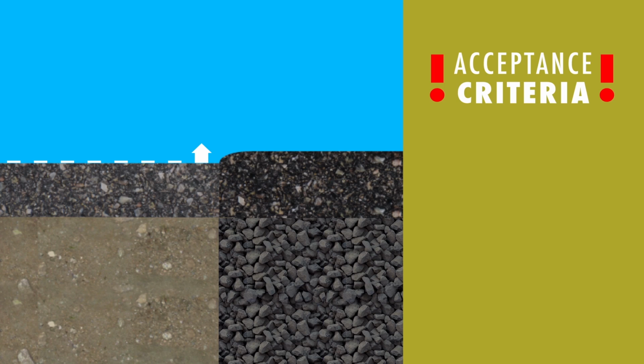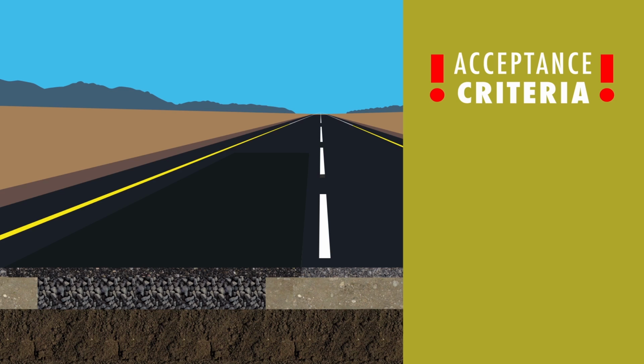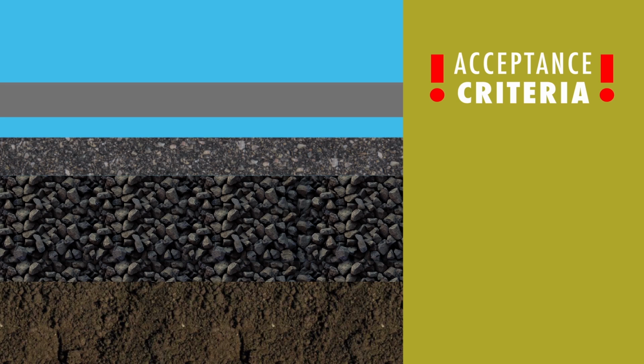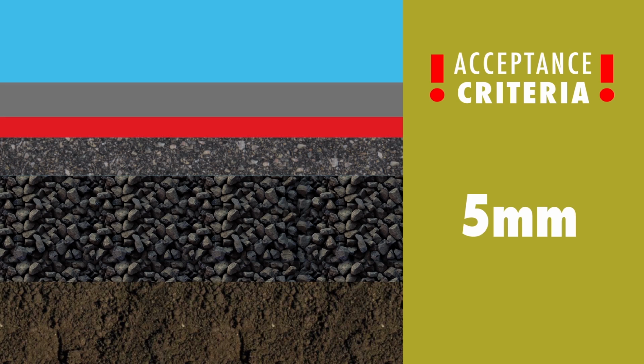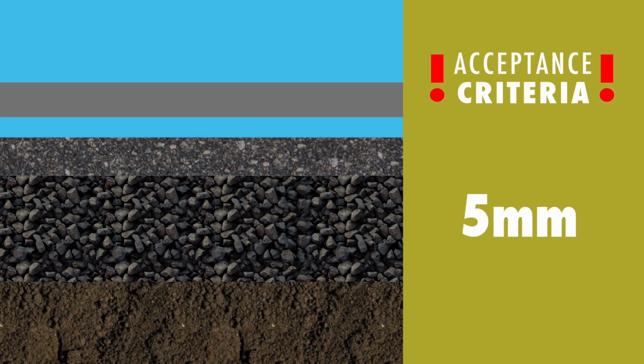Acceptance criteria for the completed patch includes: the edges of the completed surfacing must not be above the existing surface by more than 3 mm. The edges or any part of the patch area must not be below the surrounding road surface. The thickness of the asphalt surfacing at any point must be 40 ± 10 mm. When tested with a 3 meter straight edge laid parallel or at right angles to the road centerline, the surface of the area shall not deviate from the bottom of the straight edge by more than 5 mm.